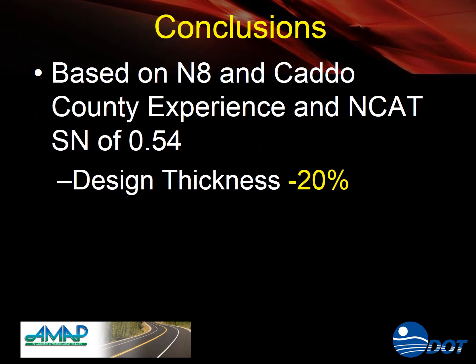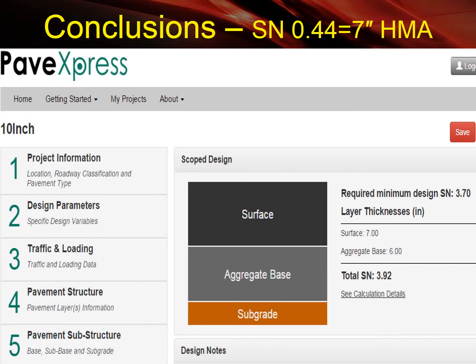Based on the performance of N8 and the Caddo County experience, and considering that NCAT has recommended changing the structural number from the old AASHTO 93 design guide from 0.44 to 0.54, you can reduce your design thickness by 20%. If you're familiar with PaveExpress, you can go through and do an analysis to verify whether what I told you was true or not. Looking at this, we have a 6-inch aggregate base and 7 inches on the surface. I set it at about 6 million ESALs and a 20-year design life.